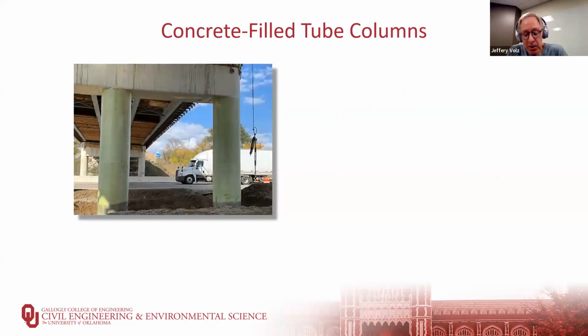There have also been some developments with, instead of using that steel tube, which can corrode, we instead use fiber reinforced polymer tubes that we fill with concrete. These actually evolved out of some of the initial applications of FRP in transportation infrastructure, which was to repair damaged existing infrastructure. And one of the first applications was actually to wrap circular reinforced concrete columns that have either partially deteriorated or in seismic regions, if it was an older design, to increase the resistance of the column. That wrapping of the FRP will help protect it from external deleterious materials and also provide confinement to the concrete, which will increase its energy absorption ability.